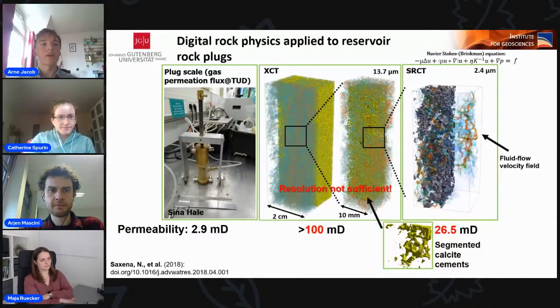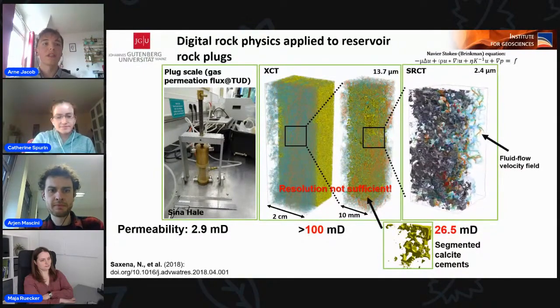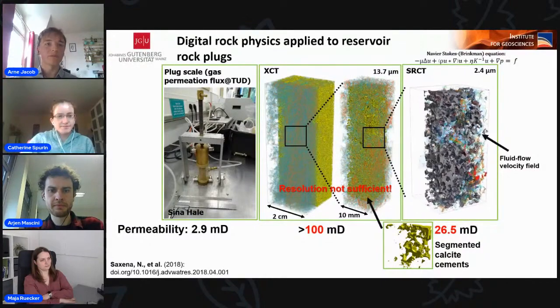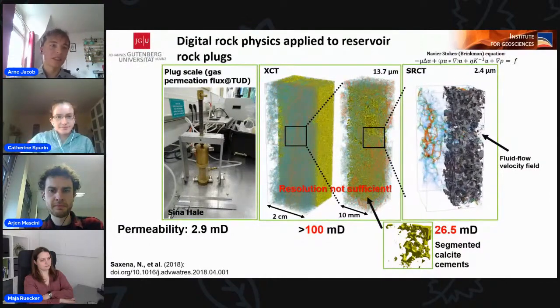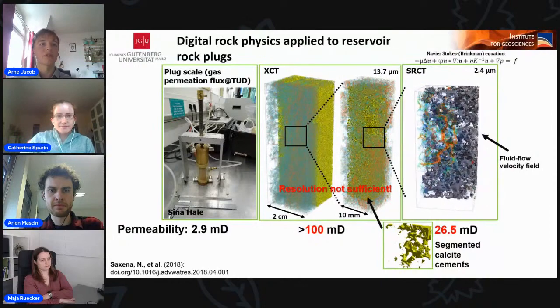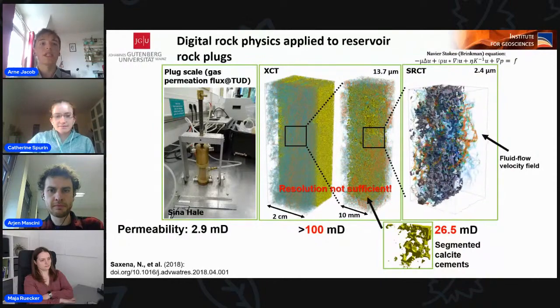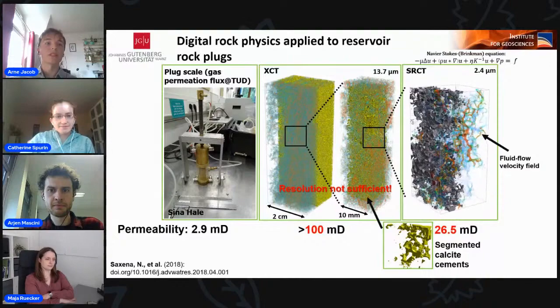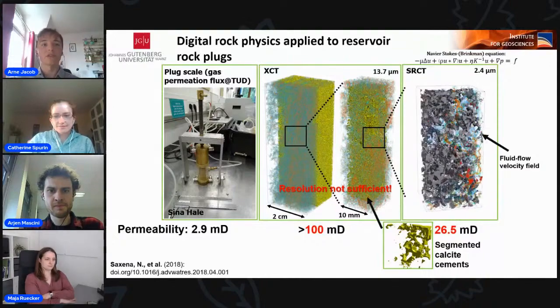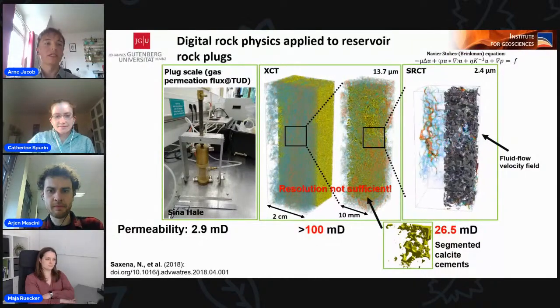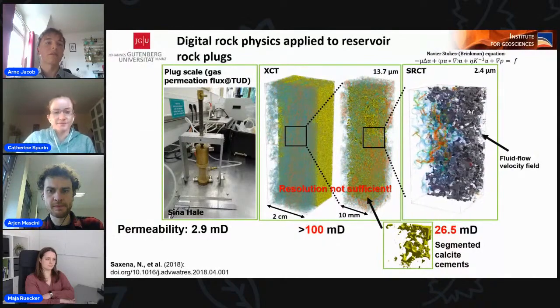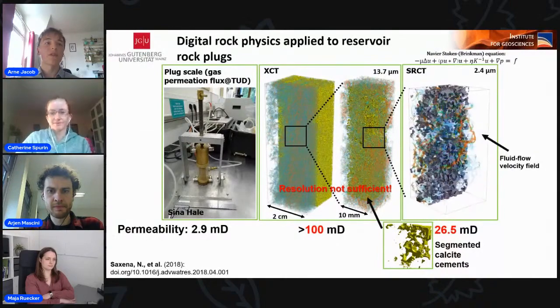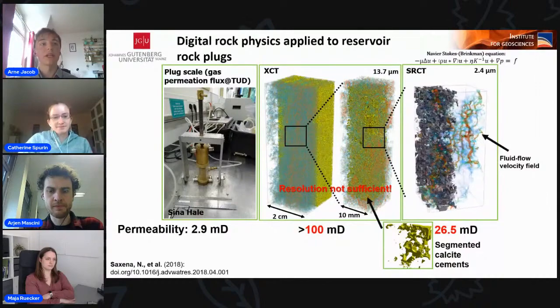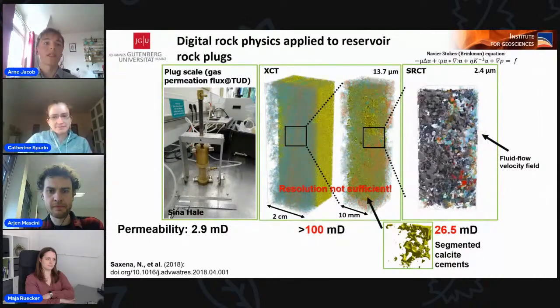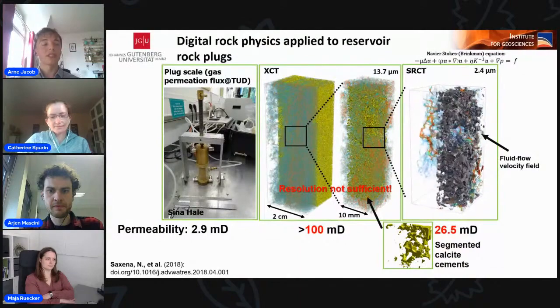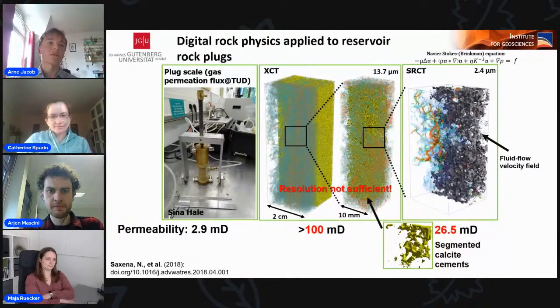Saxena wrote a paper about the operating envelope of micro-CT, which I'd like to recommend at this point. Following Saxena's recommendations, the resolution of the synchrotron images would be enough to resolve the pore throats in the smaller plug samples, while the micro-CT measurements with the bad resolutions do not. You can see that the calculated permeability for these big samples are more than 30 times higher than the measured permeability by gas permeation experiments. This resolution effect increases with increasing complexity of the pore throat network.